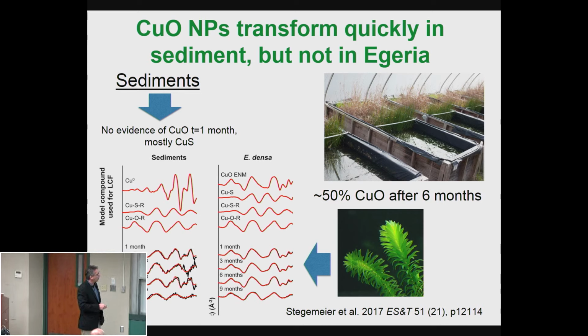What we didn't expect was a lot of the copper ended up with these plants, Egeria densa, which grows under the water in these systems. It actually filters the water, so it takes a lot of particles out. If you look closely, 1 month, 3 months, and 6 months, you'll see this little peak right here. Well, that peak is what you'd expect for the copper oxide nanoparticle. So those plants were taking up the copper oxide nanoparticles and somehow preventing them from dissolving or sulfidizing or changing. Right? So if you went in and said, okay, I put copper in and it all sulfidizes, no problem. That's fine. It does, unless it gets in the plant, and then it doesn't sulfidize right away.